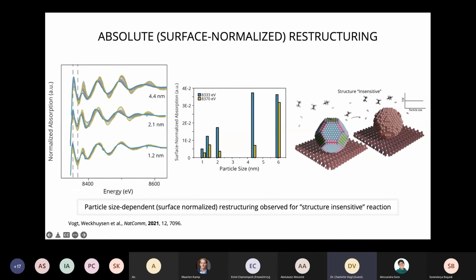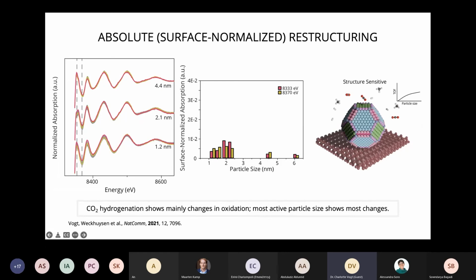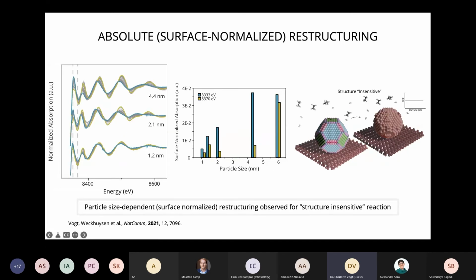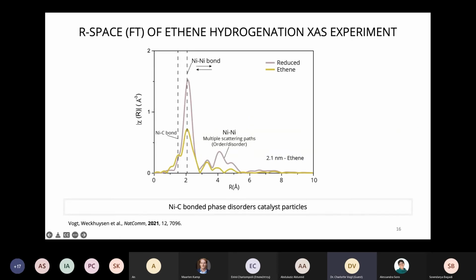For the ethene hydrogenation sample, first of all, these plots are on the same scale. Now you see that there's much more restructuring, as we already saw just qualitatively, but there's also particle size dependent restructuring. Smaller nanoparticles restructured less. Again, this is surface normalized, and larger nanoparticles restructured much more. And this is strange, that there's particle size dependent, surface normalized restructuring for that structure insensitive reaction, completely counterintuitive. So let's take a closer look at what can be causing that restructuring.